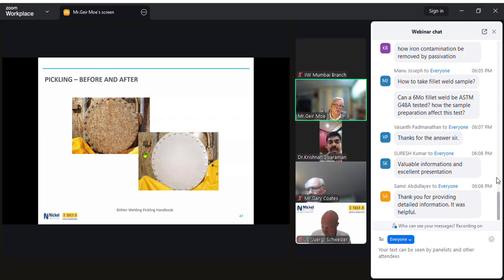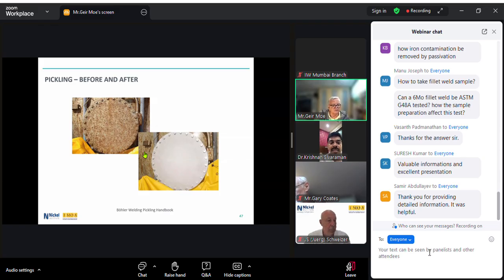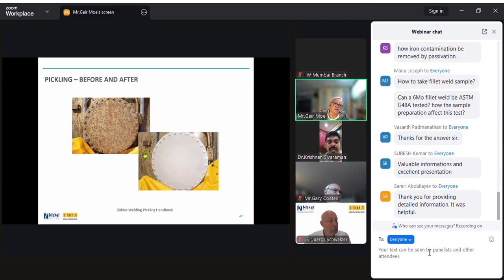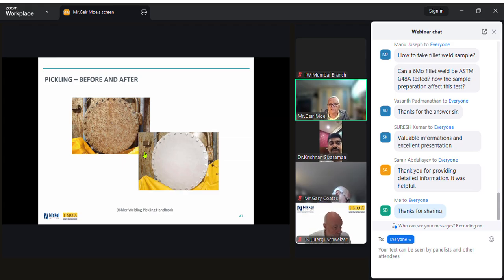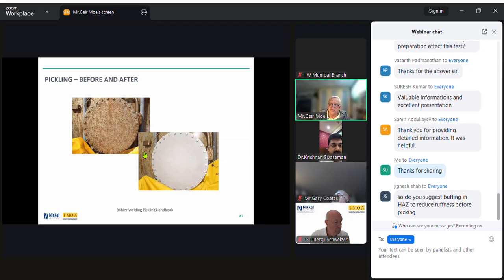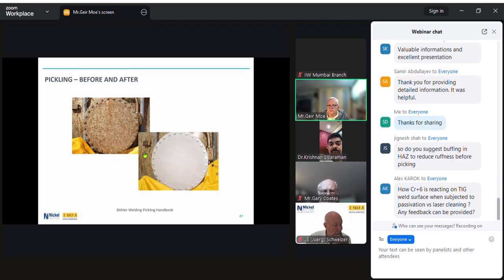In the very first slides we saw that stainless steel spontaneously forms its passive layer, and a lot of it is done within the first 10 seconds of exposure to oxygen. But it could take a day or more, maybe up to 3 days, to develop its optimum corrosion resistance. So there's nothing you need to do to reform the passive layer. It just forms spontaneously with oxygen. Yeah. But you may want to do something. It may be cosmetically unappealing, and you might need to do some fine grinding or something.